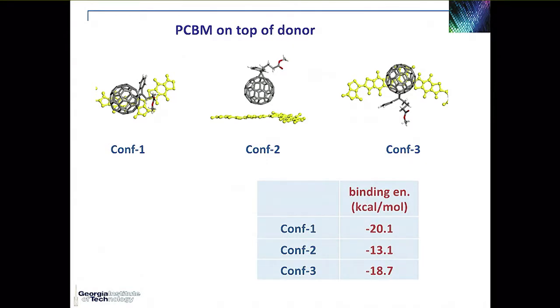And from really a very large number of calculations, we found out that when the C60, that PCBM, is on top of the chain, there are essentially three types of configurations that it wants to take on top of the chain. One in which the side chain of the C60 interacts with the pi conjugated backbone itself, one in which it is away, and one in which the side chain interacts with the side of the oligomer backbone.